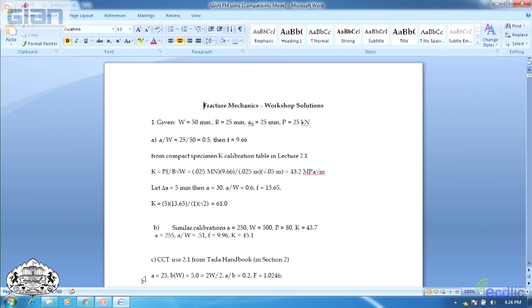One point I wanted to make in calculating this is that K increases with crack size. It increases much more quickly when you have a small structure or specimen. It increases much more quickly for a given increment of crack growth than it does on a real big specimen. So this one, K went up almost 50%. Here it only went up a few percent. So that's that. Questions on that one? Okay, let me show you the other one.